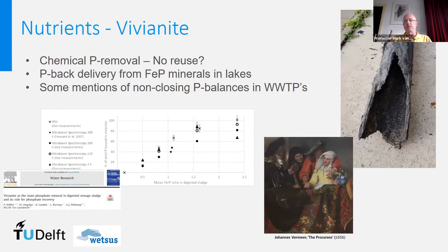And you will have about 60-70% of the vivianite already present, and you can drive that up to about 80-90% if you want, which would mean that 80-90% of the phosphate from the influent you can recover as vivianite. Now, vivianite is a nice blue mineral, which on the right-hand side picture here is scaling of a pipe at a treatment plant.